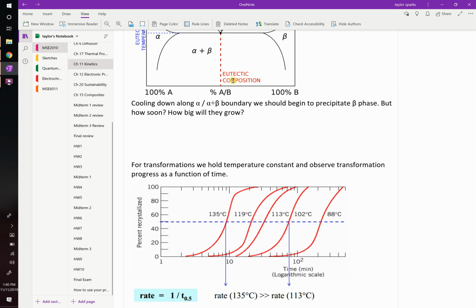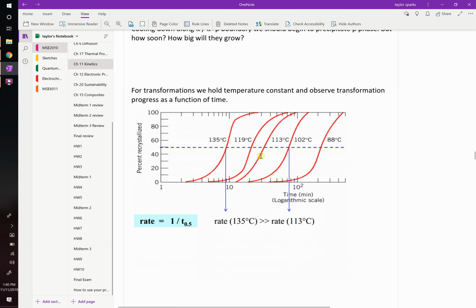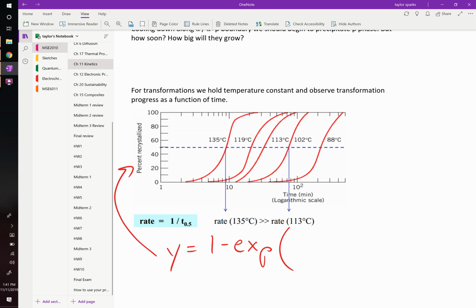So all you need to model this is a mathematical expression that looks like an S. What looks like an S? You can do it with exponentials, right? So the Avrami equation is as follows. Y, the percent transformed, right? That's this guy. Percent crystallized or transformed. Y is going to be equal to 1 minus the exponential of negative k multiplied by time raised to the n, where k and n are just constants. They're just fitting constants.